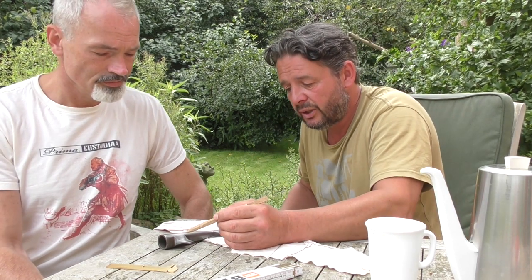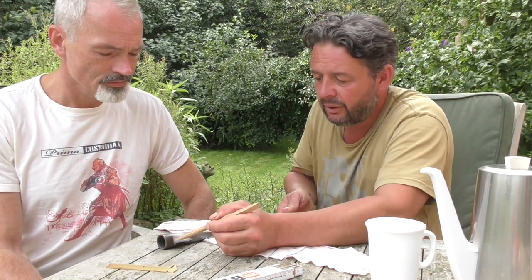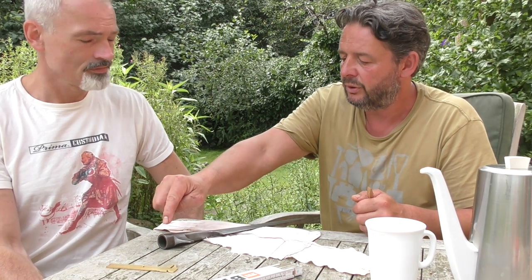But of course, the easiest way, and it's what I would do now, is to just take an electro welder and put a point here and a point there, just to fix it onto the surface. To fix it temporarily. Simply also because I'm normally alone in a forge. It's quite easy to have someone who knows the temperatures and heats one part, because both parts, the socket and that one, need to be heated to the welding temperature.